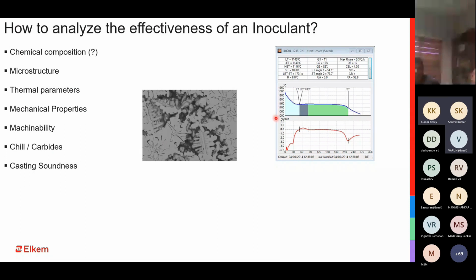When you have a good microstructure, when you have a good graphite precipitation, it means random graphite flakes of controlled length and thickness in case of gray iron, and a desired nodule count as per the section thickness in case of ductile iron. So when you are able to achieve these two, you will also achieve a very good matrix, which can be pearlitic in case of gray, and ferritic or pearlitic depending upon the grade that you are producing in case of SG. This combined together would ensure that you also have a very good machinability on your casting.